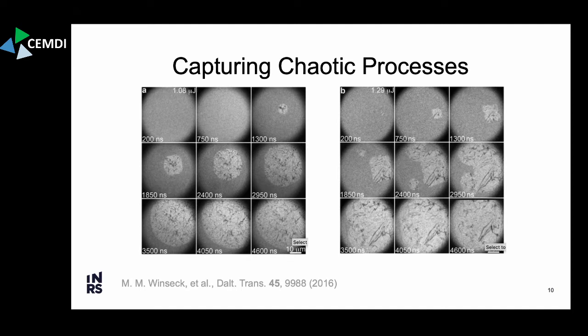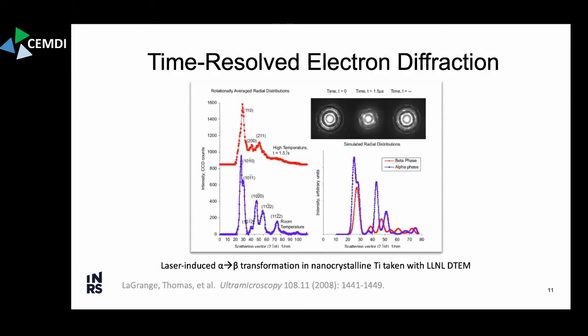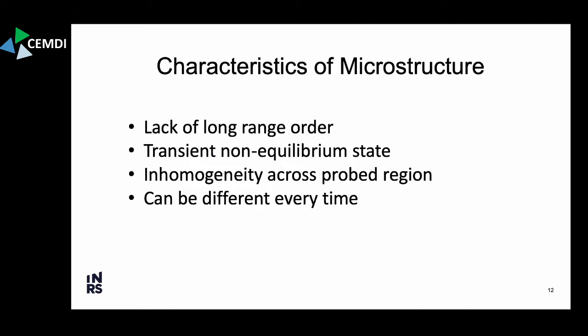And so this has been used by the group at Lawrence Livermore, the people who developed the DTEM, as a proof of principle experiment to show we can actually capture these sort of chaotic, irreversible phase transformations. Similarly, you can do time-resolved electron diffraction in this microscope. This is showing the transformation from alpha to beta nanocrystalline titanium, and you can capture the diffraction pattern as well as the image in the microscope. But this poses a problem because